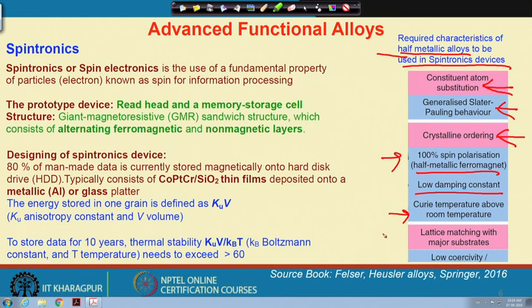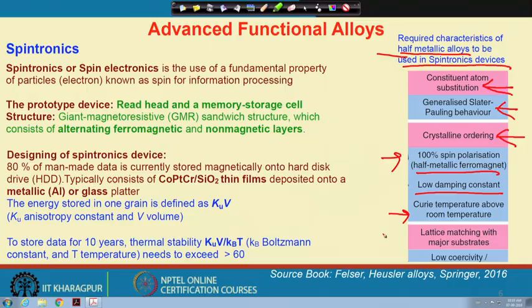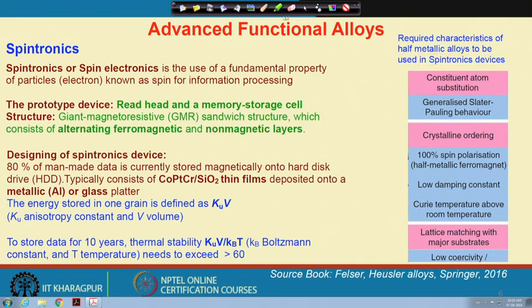because if we have to store magnetic data and the Curie temperature is very near room temperature, then all hard disk drives will fail, right. So, we need a very high Curie temperature to store room temperature data, and the lattice matching with the substrate is also important, because we have to grow those films on top of aluminum or some glass plate. So, the substrate is also important, as well as low coercivity, and it should be soft magnetic in nature. So, these are the very important aspects of a half metallic material to be used for spintronics application.